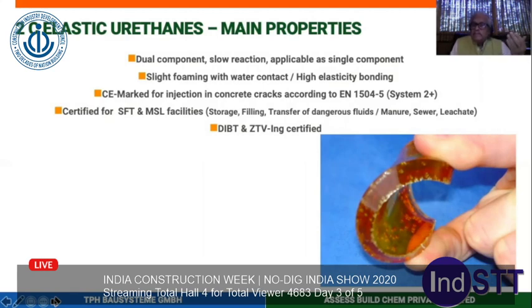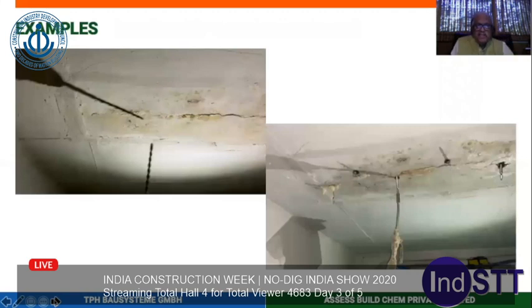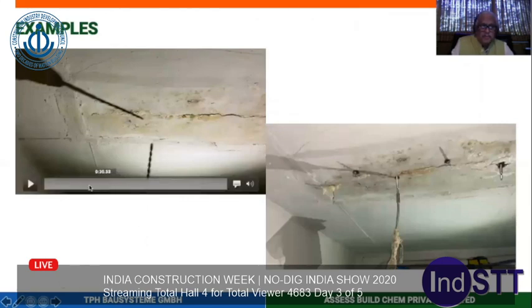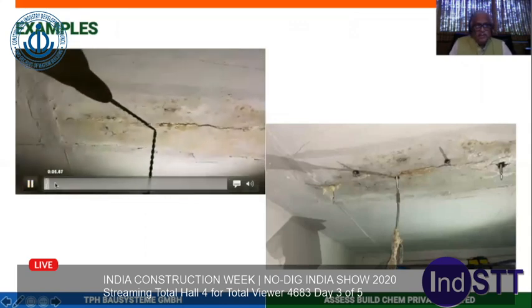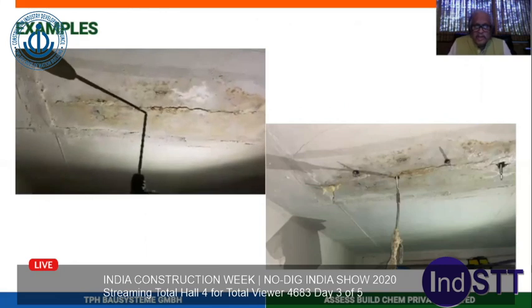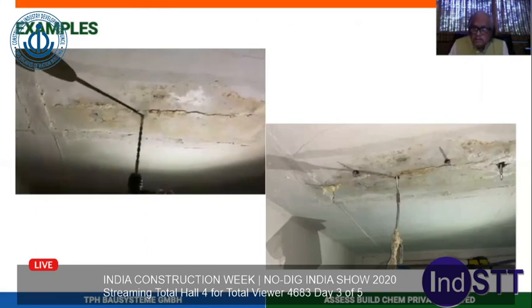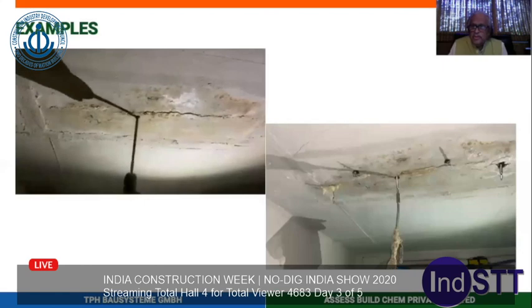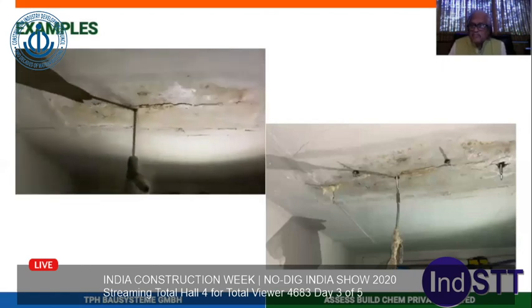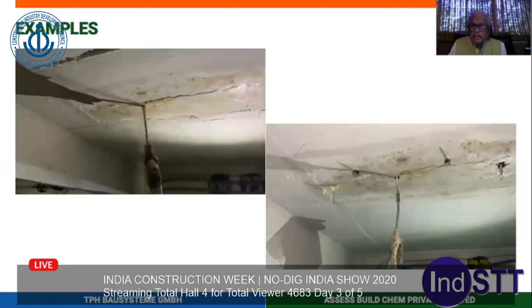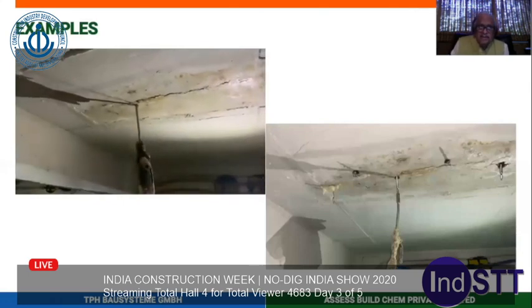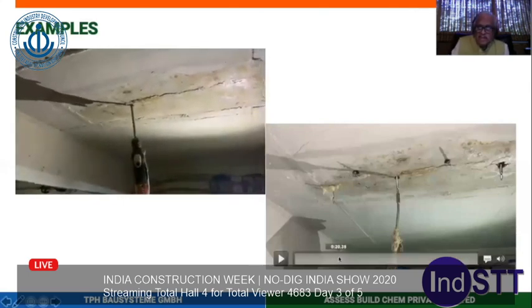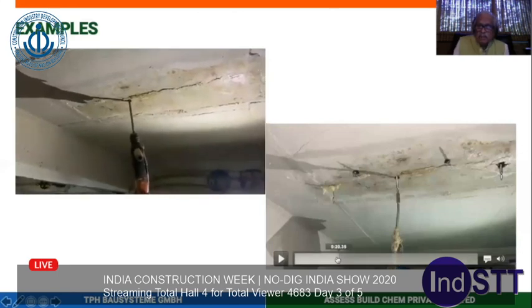You can inject them. They are not sensitive to moisture. In cases like this, which you will normally see in basements, in underground structures, in parkings, you can see the water coming inside. This is the method of injection. You have to drill the holes at a 45 degree angle. You have to put the mechanical packers inside, fix those packers so that the material reaches the center of the crack, and then start injecting the material with proper machinery, with proper connections.